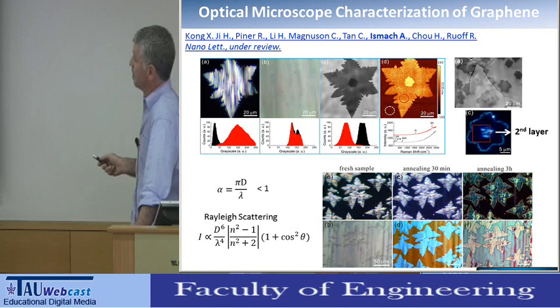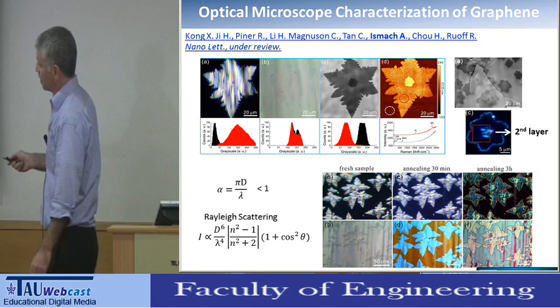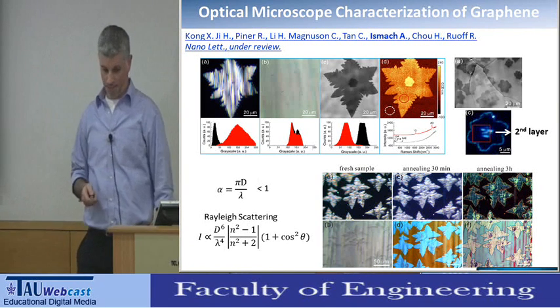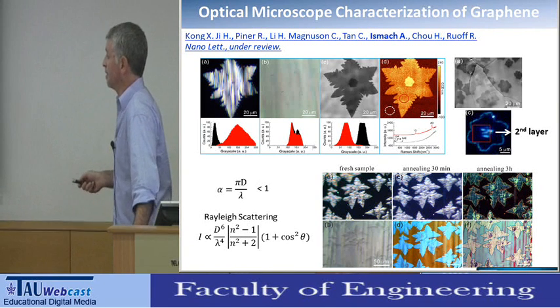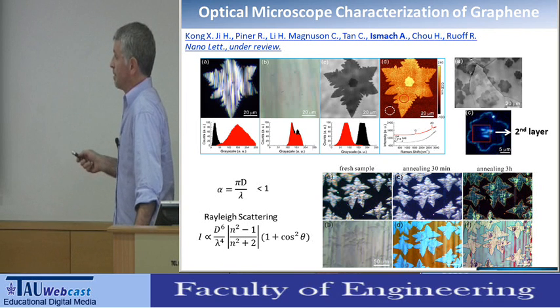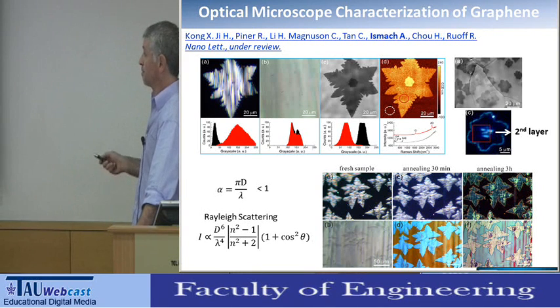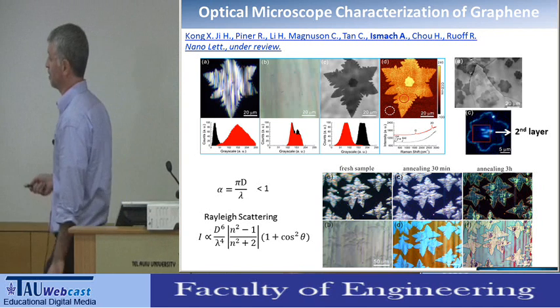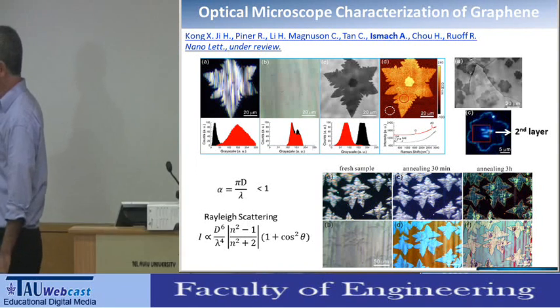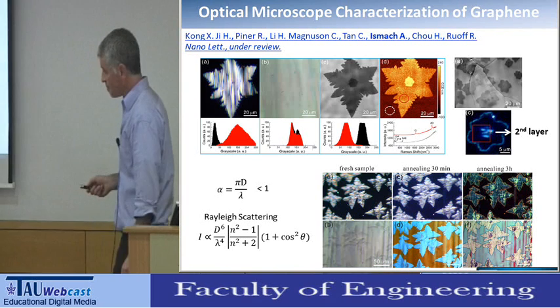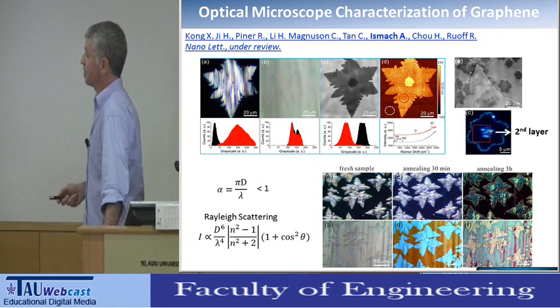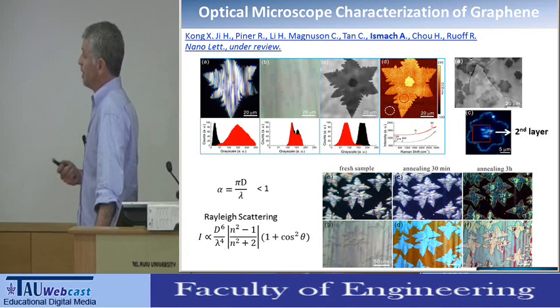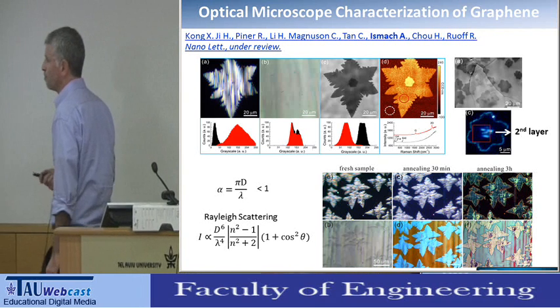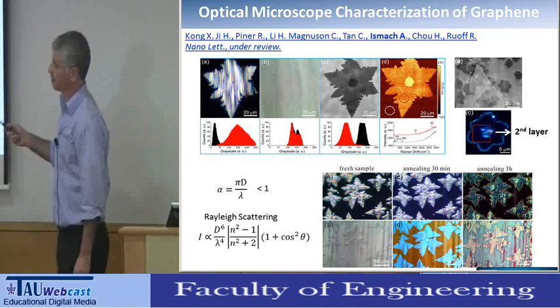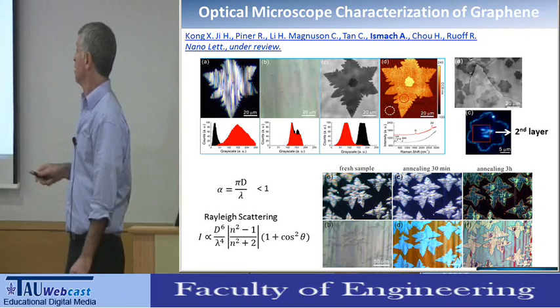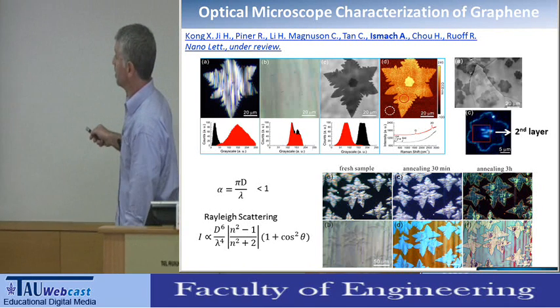So of course you can show that in dark field microscopy, the scattered light is the one that you are going to see, and in our case, we can see that the limit of detection is about 2 to 4 nanometers nanofacet height. Smaller than that, we can't see it in the dark field.